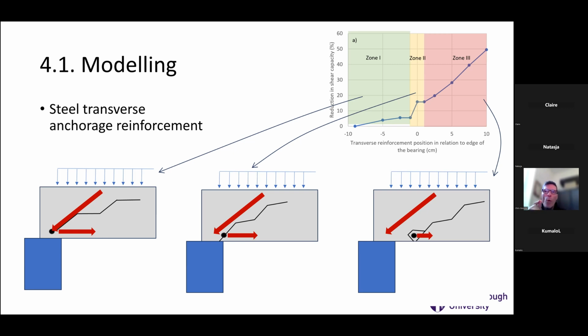But quite quickly, if you move away from the bearing, so that steel bar isn't over the bearing, then you start eating into your safety factor and your capacity too much. And then it depends on all the other factors, as in the loading being the main one, the size of the bearing, the condition, the quality of the RAAC, the compressive strength. If everything is perfect, maybe you've got a bit of leeway there. If you've got other defects in your structure, which many 50-year-old buildings have, then it could fail with that bar not very far from the bearing. So this is the key concern worrying the structural engineers, which very much informed the guidance and hence the closure of the schools.